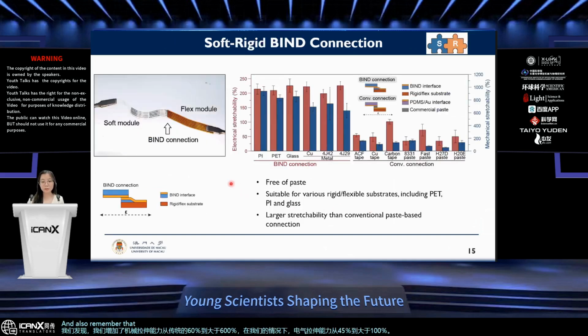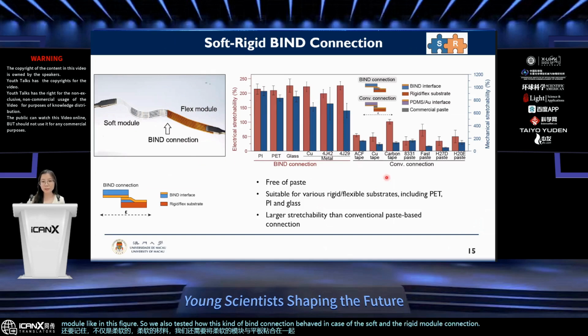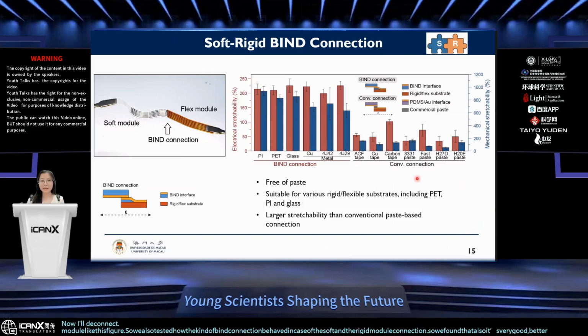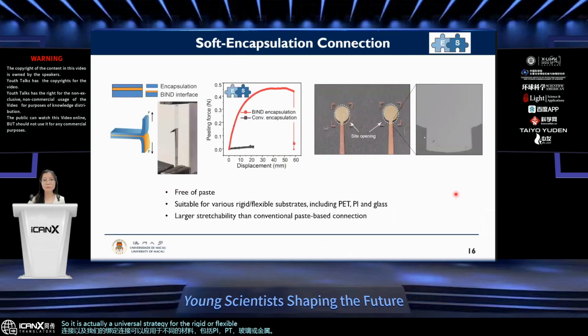And also remember that not only the soft materials, we also need to bond the soft module together with the flexible module, like in this figure. So we also tested how this kind of bind connection behaves in case of the soft and the rigid module connection. We find that it's also very good, better than the conventional paste-based connection, and our bind connection can be applied to different materials, including PI, PET, glass, or metal. So it is actually a universal strategy for the rigid or flexible module connection.